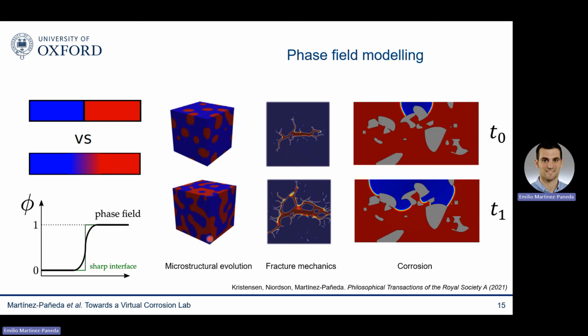It has also very quickly become the dominant technique to simulate fractures, and you can see here why. Very complex cracking phenomena can be captured. This is the output of a simulation. You can see here crack branching, coalescence, nucleation of secondary cracks. And we and other groups in the US and Asia have recently shown that this paradigm can also be extended to corrosion. The phase field can be used to describe the evolution of the electrolyte-metal interface, the corrosion front.